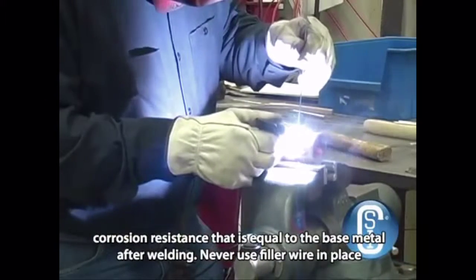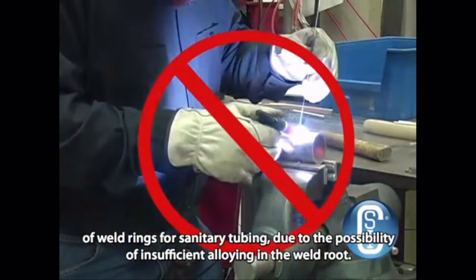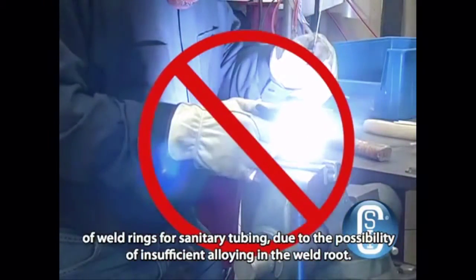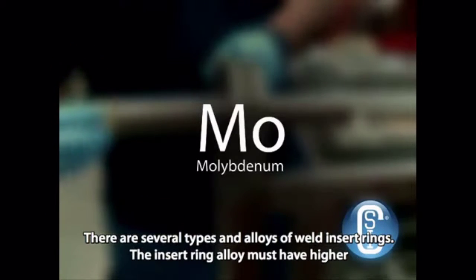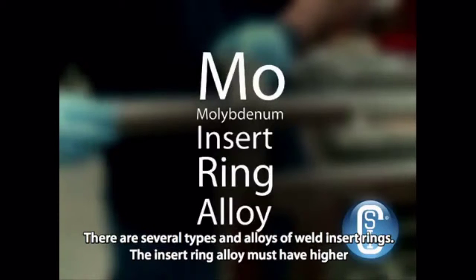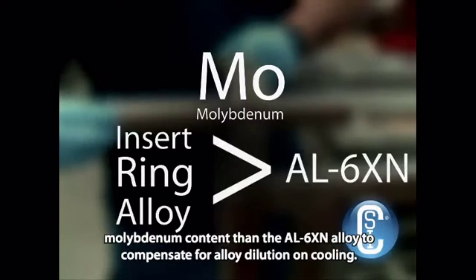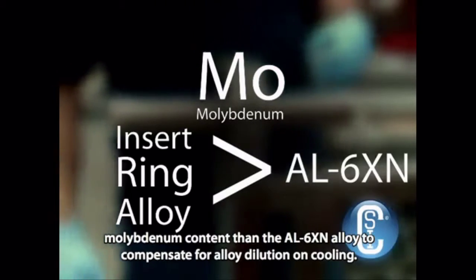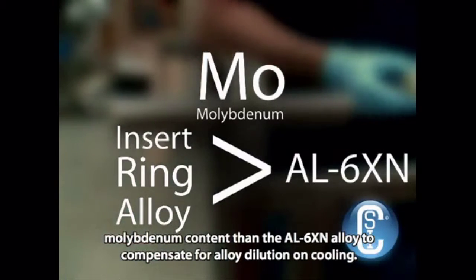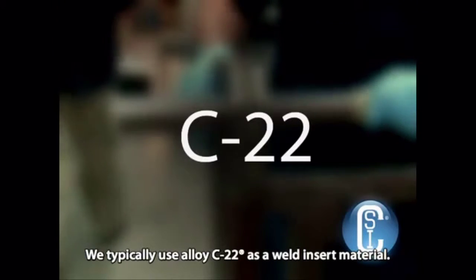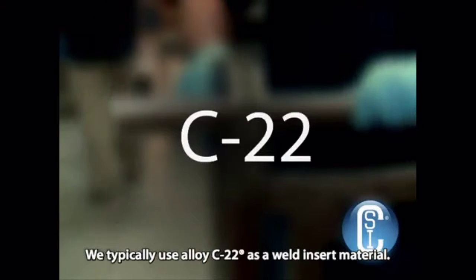Never use filler wire in place of weld rings for sanitary tubing due to the possibility of insufficient alloying in the weld root. There are several types and alloys of weld insert rings. The insert ring alloy must have a higher molybdenum content than the AL-6XN alloy to compensate for alloy dilution on cooling. We typically use alloy C22 as a weld insert material.